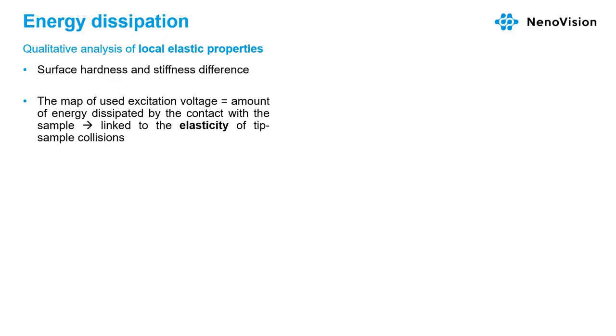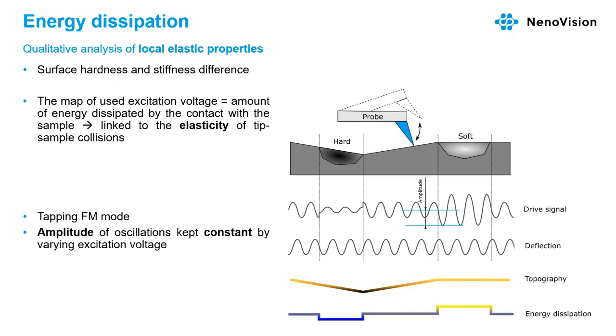And so energy dissipation maps the local elastic properties, obtaining qualitative information about the sample surface. The elasticity of the tip-sample collisions is linked to the energy dissipation, and the amount of energy dissipated from the sample is linked to the excitation voltage, which the feedback uses to maintain the same amplitude of oscillations.